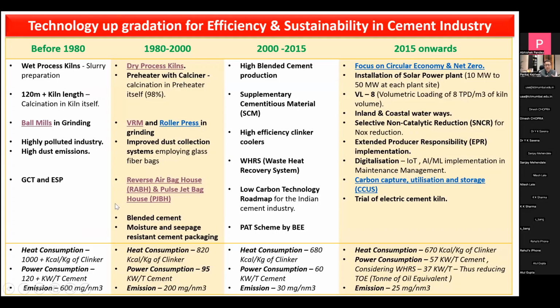At that point of time, the pollution equipment was also quite primitive. We were using the gas conditioning towers with ESP. All this led to a very high heat consumption of more than 1000 kilocalorie per kg of clinker. Even the power consumption was very high, nearly 120 kilowatt per ton of cement, and emissions were huge, nearly 600 milligrams per nm cube.